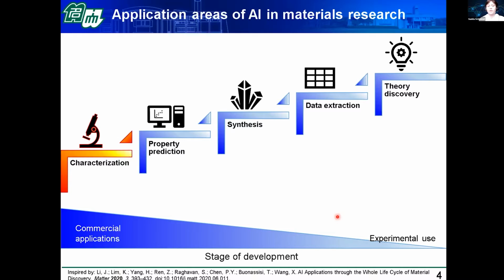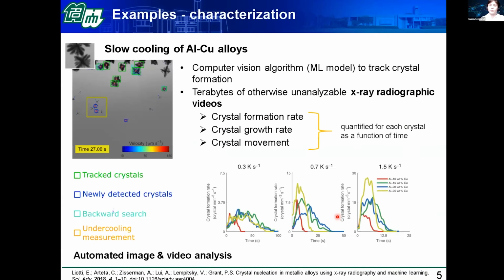So first I would like to show an example for applications in characterization. Many of those applications focus on automated image analysis. The example that I'm showing does video analysis of X-ray radiographic videos taken during the slow cooling of aluminum copper alloys. And the authors were able to automatically and efficiently analyze those data to detect the formation of crystals and to determine the formation rate, growth rate, and movement of the crystals as a function of time and some process parameters like the cooling rate and composition. And such analysis methods seem to be already rather widely applied.